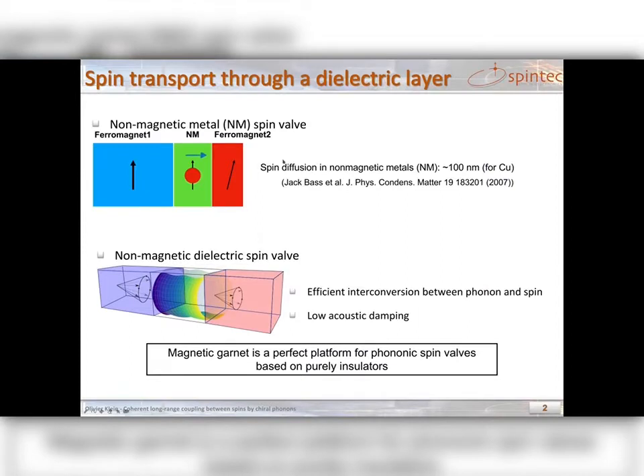So let me start with the motivation of our work. In a conventional spin valve structure, a non-magnetic metal spacer is used to transfer spin polarized electrons at Fermi energy from ferromagnet 1 to ferromagnet 2. And that affects the magnetization state of ferromagnet 2. But the short spin diffusion length of electron is the limiting factor that decides the thickness of this non-magnetic spacer.